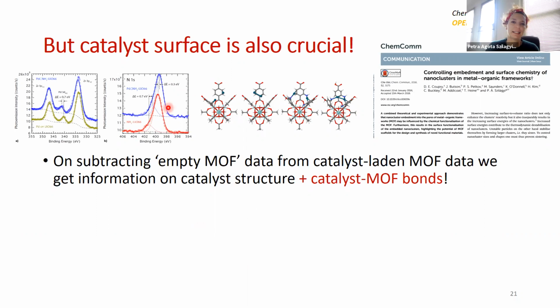So what that means is that in such a case, we should be able to see palladium-nitrogen bonds in the pair distribution function data. And the other thing I would like you to recall is the thermal desorption spectra, where you could see perhaps a little dip in the hydrogen desorption of the amino groups. So of course, if the amino groups are bonded with the palladium, they will not be able to absorb hydrogen as well. So this is the real reason why the desorption of hydrogen from the amino group is much lower in the case of the palladium-laden framework.